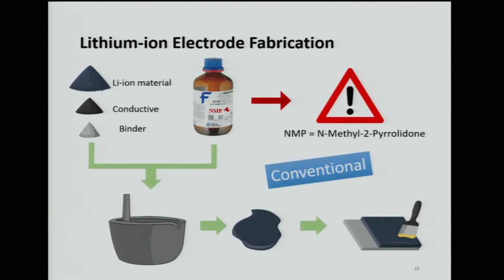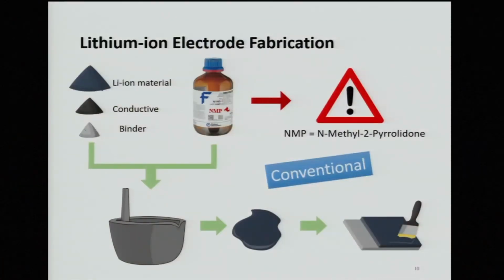So you're probably sitting there wondering, well, then why do you use NMP? Well, that's because of the binder. The binder is highly specialized because it doesn't degrade during battery use. It's also very picky. It only wants to dissolve in NMP. And we need it to be able to dissolve in NMP so we can make a uniform coating among these three components. That actually brings us to the second reason why this conventional technique isn't very appropriate.